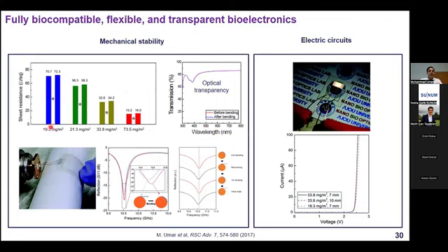If we have silver nanowire in the silk with different densities, we bend each of the samples 1,000 times, and we see there is very slight change in the final resistance after 1,000 times bending. This is just a 1% or 2% change in the sheet resistance of this conductive silk film, but there is no change in the optical transparency of the silk. So this means there are no cracks or other phenomena happening in the silk.